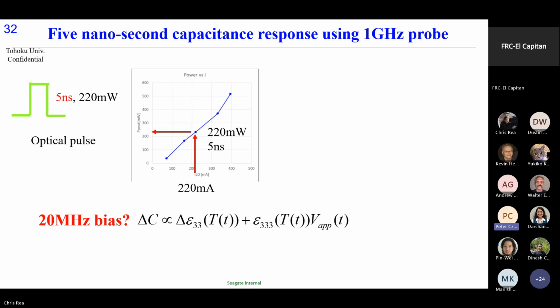Then we reduce the pulse duration to 5 nanoseconds, but in this case, we cannot detect this part. But at least this system is applicable for the nanosecond order capacitance response to be detected. So we try to detect the linear capacitance response at the speed of 5 nanoseconds.